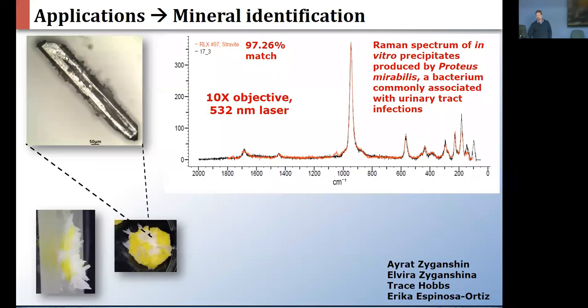So here's actually an image of one of these beautiful struvite crystals that was taken from the sponge specimen. And what you can see here is this is against the KnowItAll database. So the black is the spectrum that was acquired, and then the red is the spectrum in the database. And you can see it's a really darn good match. So this really assured us, yes, what we see is struvite. This is fairly straightforward, but still requires a little bit of pre-work, trying to understand how to do this inside the capillary. This one was just a clean crystal on a wafer, basically.